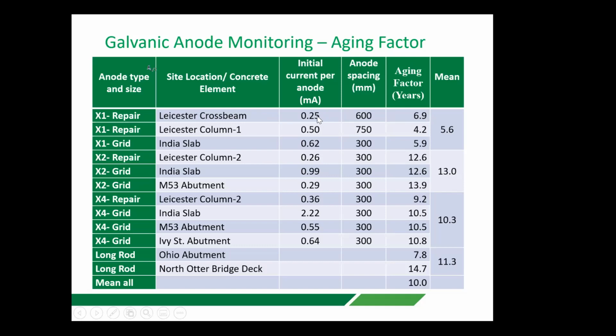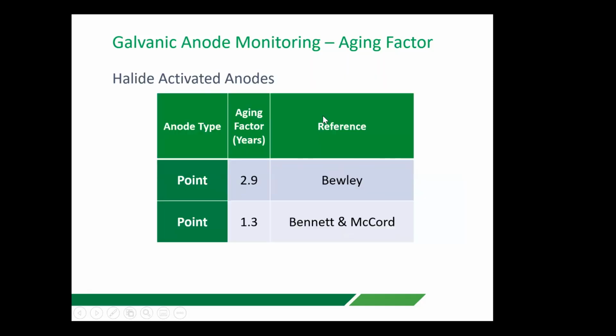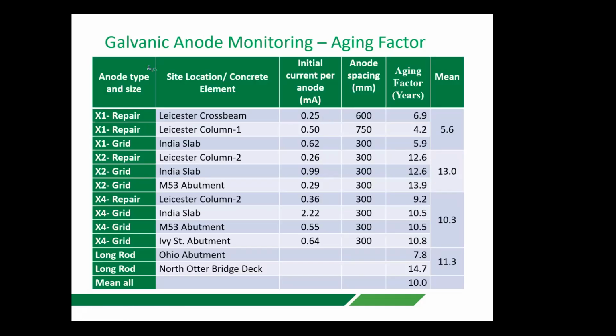But it tends to be related to that early current density. So in the case of the one that I talked about, we were talking about an initial current density of about 0.25 milliamps per anode. In the adjacent one, that was at the spacing of 750, everything else was the same. It's the same concrete structure, the same amount of steel, therefore the steel density is very similar. The environment is similar. The initial current from exactly the same anodes was 0.5, double the current output of the first lot.